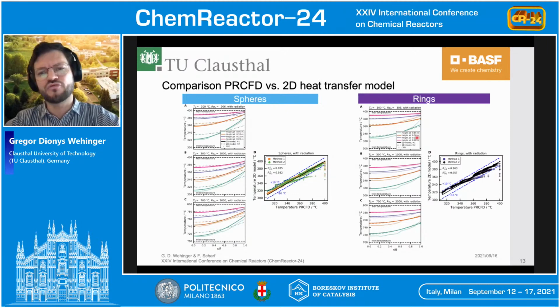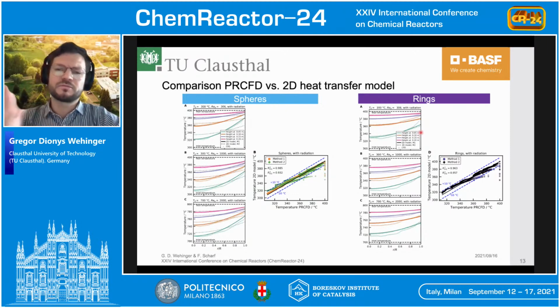On the other hand, for the rings, both methods give more or less the same radial temperature profiles. However, we see a pretty large deviation between this pseudo-homogeneous model and the PRCFD simulation. Obviously, this wavy contour cannot be captured by the model, but on the other hand, we also see deviations in the bed center as well as really close to the wall. The parity plot reveals that.